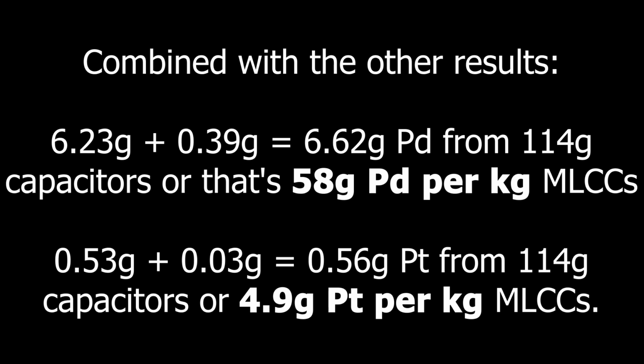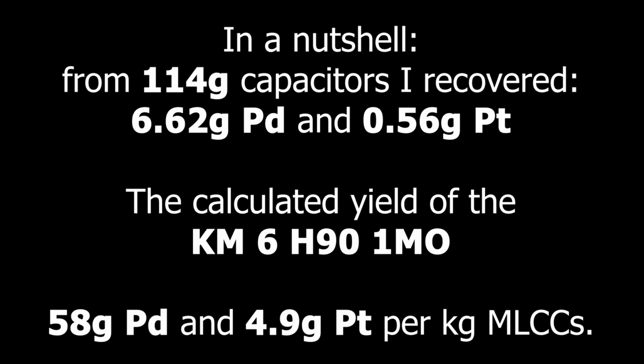0.53 grams plus 0.03 grams equals 0.56 grams platinum from 114 grams capacitors. Or 4.9 grams platinum per kilogram MLCCs. In a nutshell, from 114 grams capacitors I recovered 6.62 grams palladium and 0.56 grams platinum. The calculated yield of the KM6 H90 1MO is 58 grams palladium and 4.9 grams platinum per kilogram capacitors.